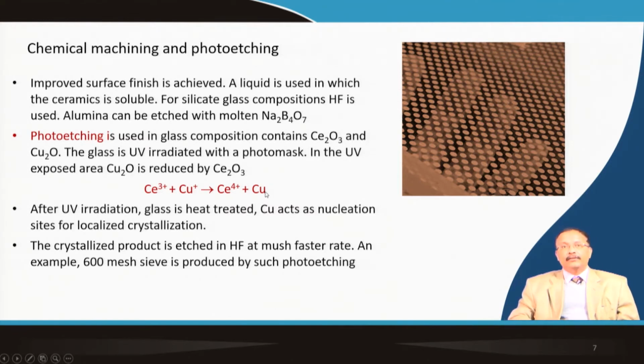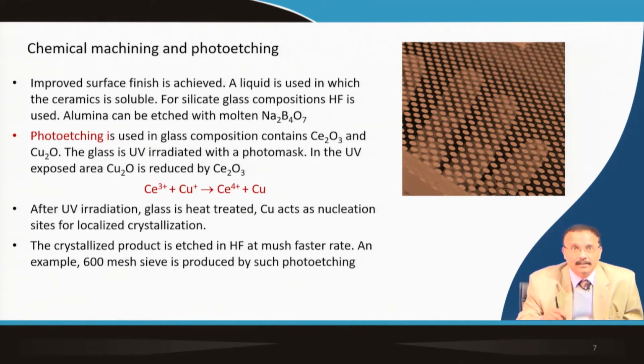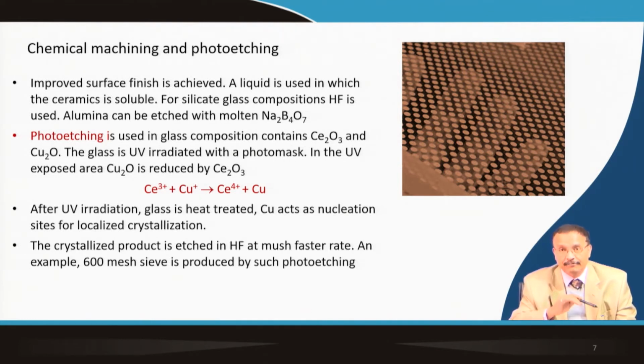After this UV radiation, the glass is heat treated. Then copper acts as a heterogeneous nucleation site and it leads to local crystallization. You may like to dissolve this crystallized product by treating it with HF. HF will eat this crystallized product at a much faster rate. So, you can get a mesh as small as, say, a 600 mesh sieve, with very fine holes, by this chemical machining followed by photo etching followed by chemical machining. You can make a very fine 600 mesh glass block.